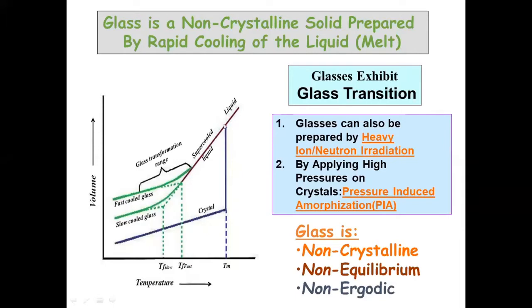But supposing I remove heat energy, the enthalpy, the heat content of the liquid very rapidly, very suddenly, then this abrupt decrease in volume you will not see, but you will see a continuous decrease in volume. Most of the materials shrink when you cool them, and it will enter what is known as the supercooled liquid region. Here it is still a liquid, but it is much colder than a liquid because I have removed heat from it. And then it goes through a continuous transition, and this is known as the glass transition range or glass transformation range. And we get a solid which has very high viscosity of the order of 10 raised to power 22 poise, and it is also rigid like a crystal.